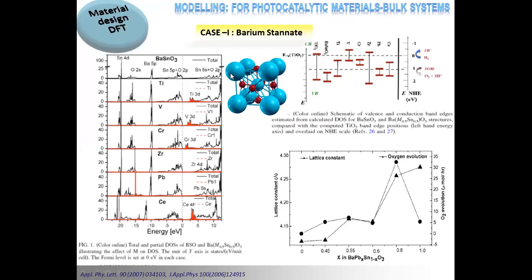Now, on the left hand side, you can see a graph of electronic structure which is simulated from the software. On the right side, you see the same graph where we have the redox levels of the water molecule, and the conduction band and valence band of each of the systems, like TiO2, barium stannate, and then doped systems of these metal ions, drawn on this particular graph. This tells us what the possibilities are with respect to a particular type of material and its suitability for the photocatalytic application. TiO2, as I said, is a standard material and has a very large band gap also.